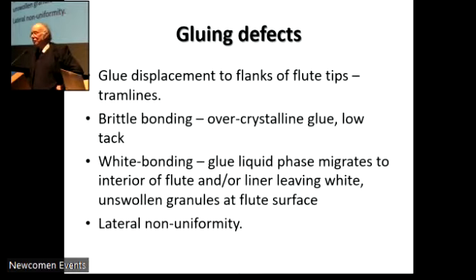The solution to that is quite simple. You increase the speed of the corrugator. That reduces the dwell time for heat input from the preconditioners and the heating rolls, and therefore it restricts the amount of swelling of the starch granules before they're rammed up against the liner.